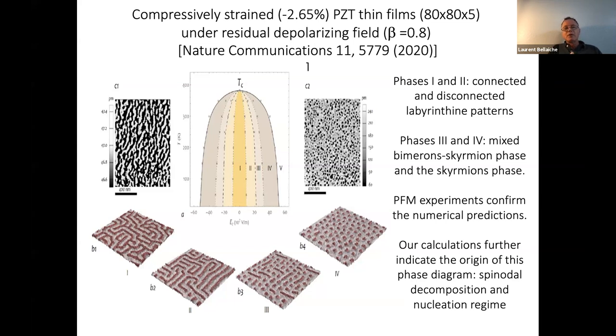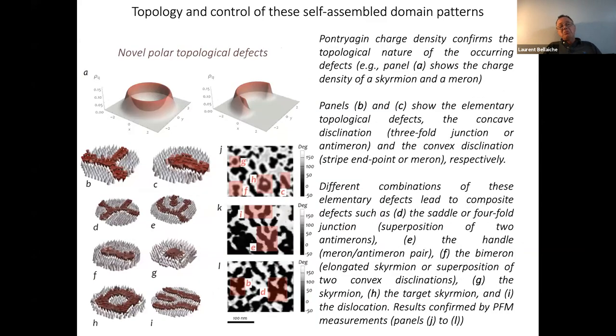I refer to this paper, but technically it's non-equilibrium physics, and you have different origins of the phases. One is called spinodal decomposition. The other one is called nucleation regime. But I just want to show you that now with effective Hamiltonian, in fact, since 2003, you can do a nanostructure with no big deal. And you can also really study topological effects.